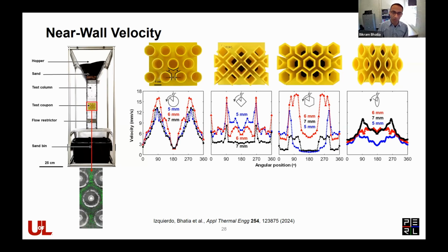So we looked at different tube geometries, including circular tubes, which are most common in the industry. We also looked at diamond shapes and hexagons, which have been reported in the literature before. The claim was that their performance can be better than the circular tubes. And we also came up with airfoil shape structures, inspired by airfoil wings in aircraft. The values shown here are near-wall velocity, around 10 particle radii from the central tube wall. Using PIV analysis, we measured the velocity around these tube walls for all these different geometries, and it is shown here as a function of angular position.